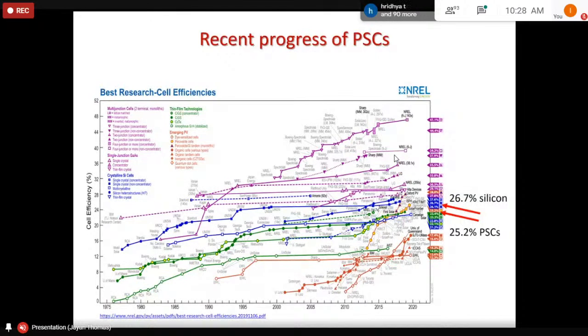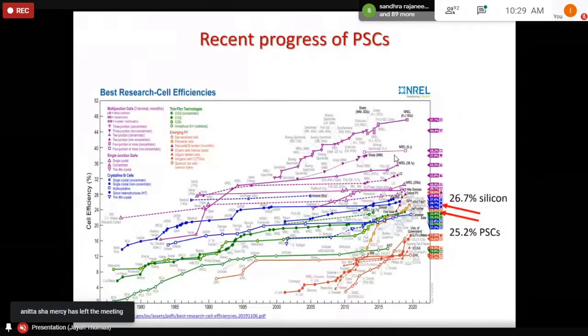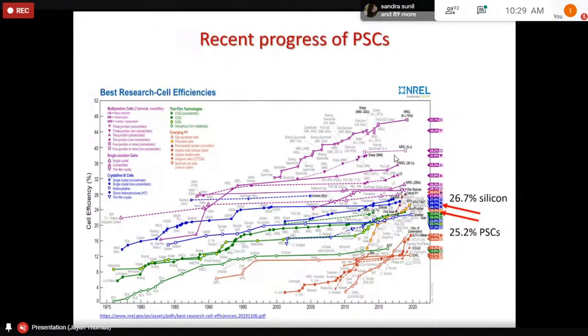It started back in 2008, 2010, that period. And the initial efficiency was even less than 10%. Within just 10 to 12 years, the solar conversion efficiency jumped from about 8% to about 25.2%, a very recently reported efficiency. So this is a very promising material, basically because these solar cells can be developed by solution processing, and it is made from earth abundant starting materials.